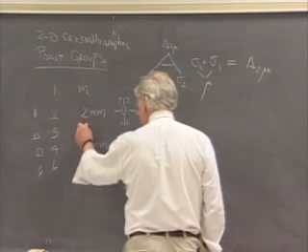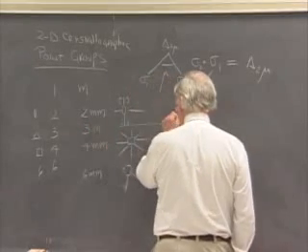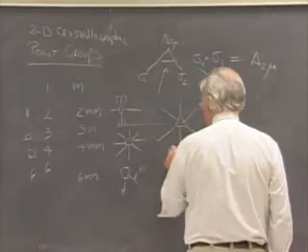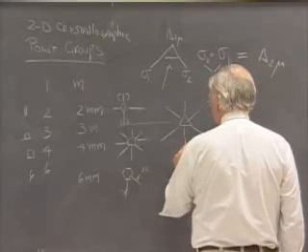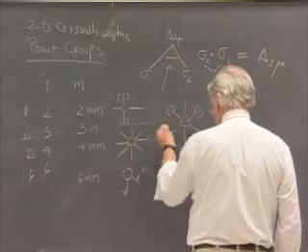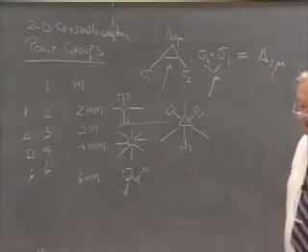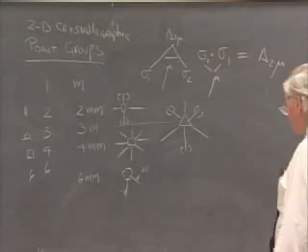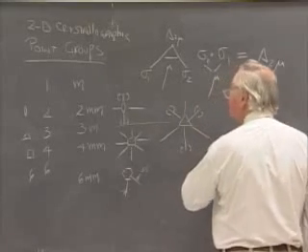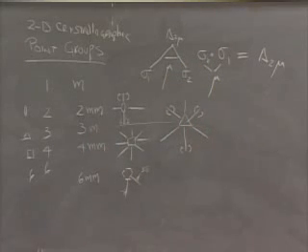And the one that I left out is 3m, not 3mm, because a three-fold axis has mirror planes separated by 60 degrees, and the same thing goes on at each of these mirror planes. A pair of objects hanging at one end of the mirror plane, the other end is unadorned. So they all behave the same. There's only one kind of mirror plane. The threefold axis maps one mirror plane into another, and so you know they have to be the same. Therefore, only one m appears in the symbol.